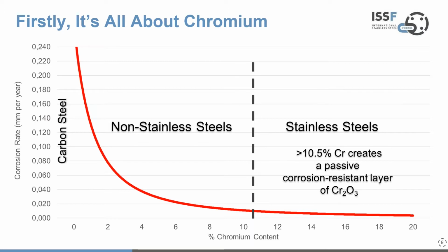On this graph here, you have the corrosion rate shown on the y-axis on the left, and you have the chromium content from 0 up to 20% in this case shown on the x-axis on the bottom. The red line indicates the corrosion rate as the chromium content increases. So what you see is that the carbon steels, to the left of this chart, rust. You have the non-stainless steels in the midsection of the chart, they rust but at a slower rate. And then to the right of the black dotted line, you have stainless steels. These are the steels with greater than 10.5% chromium content, and they resist corrosion, and you're almost at a flat line position across those higher chromium content products.